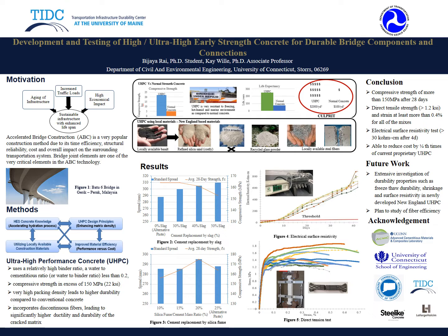Ultra-high performance concrete, in short form UHPC, is a cementitious composite with a relatively high amount of binder in comparison to conventional concrete. It is designed to use a water to binder ratio of less than 0.2, achieves compressive strength in excess of 150 megapascal or say 22 ksi, and addition of tailored discontinuous fiber reinforcement leads to significantly high ductility and durability of the cracked composite.